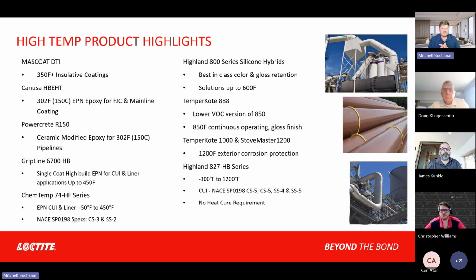So some of the products that I would like to kind of highlight today, and then we'll do a quick deeper dive on the Highland 827, which is kind of our workhorse into this high temperature space. So Mascoat insulative coatings, right? 350 Fahrenheit. It's a high temperature for an acrylic coating. It's a specialty acrylic binder and allows it to have continuous operating of 350.